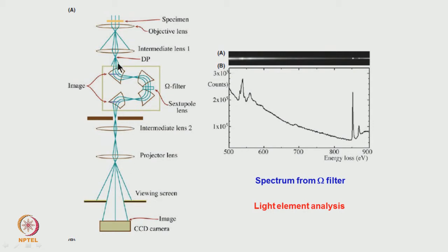The same thing can happen in the case of diffraction also, because we know that when the sample is thick, Kikuchi diffraction takes place, which gives rise to a uniform background on the sample surface. This background could be removed very easily by choosing electrons which are only elastically scattered, because normal diffraction takes place only because of elastic scattering.